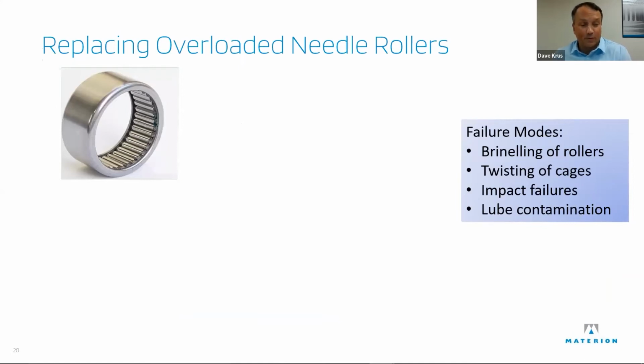But what can go wrong is you can get flat spots on the rollers if you overload it in a stationary condition. That's called Brinelling. The cages can twist. I'm sure people have seen that, where you have the cage twist and needles are all over your engine. That's not a good thing to have happen. And impact failures. Again, you could blow the cages apart with an impact. And if for some reason your filters aren't doing the job, or you're in a dirty environment, lubrication contamination is bad for those small little spaces in the needle roller.